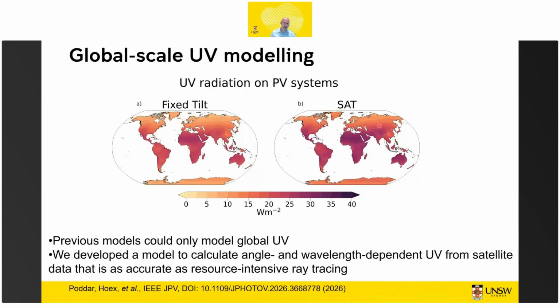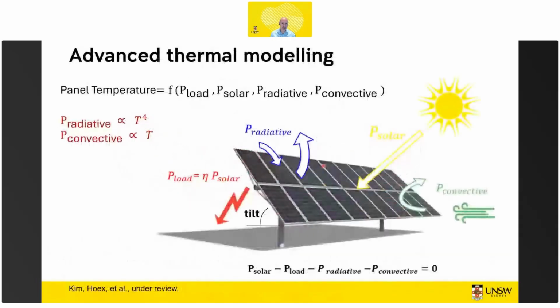And you also see that fixed tilt is a lot less, because you're not following the sun. So it's quite obvious if you think about it, but we've been able to quantify that. And this also means that one test at a certain dose means quite different results depending on the location, and we're helping our partners with that. Then another factor is temperature.